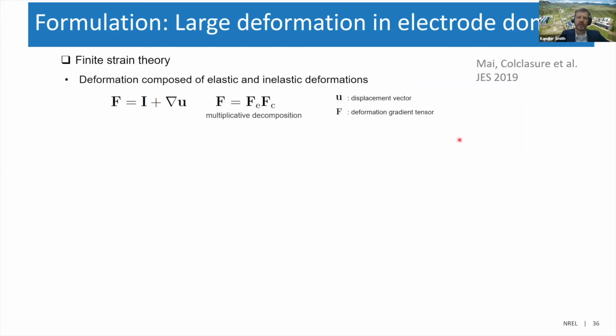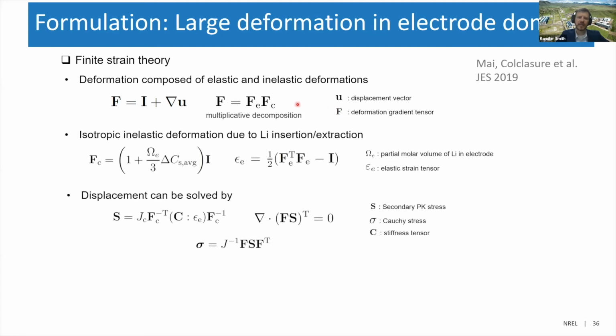This is the work of Weijie Mai and Andrew Colclasure, published last year, and he has started with finite strain theory to describe the large deformation mechanics. And this deformation tensor F here, it has a multiplicative decomposition. The Fe is an elastic term, and then the Fc is a concentration dependent term. Usually when you see small deformation models, these are additive. And in this particular case, for large deformation, these factors are multiplicative.